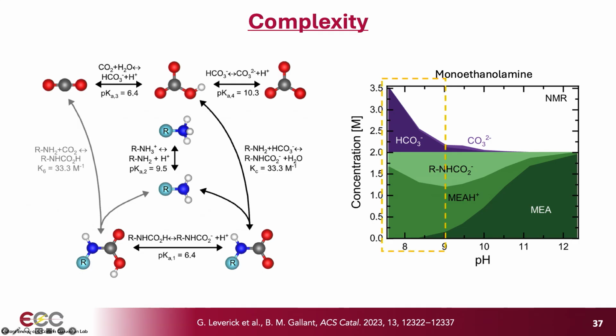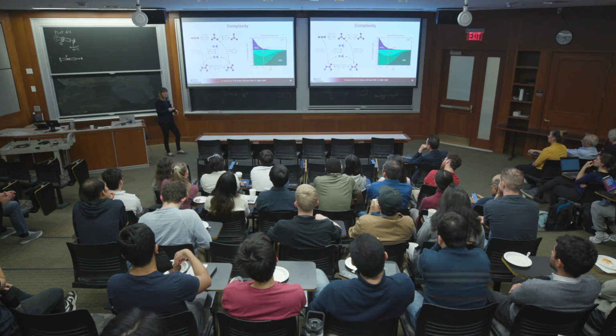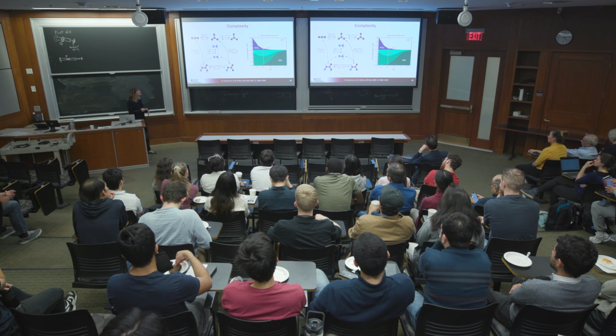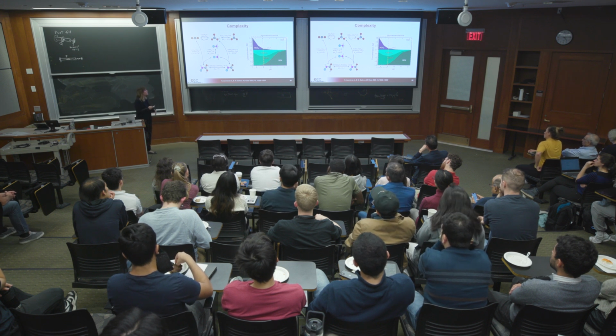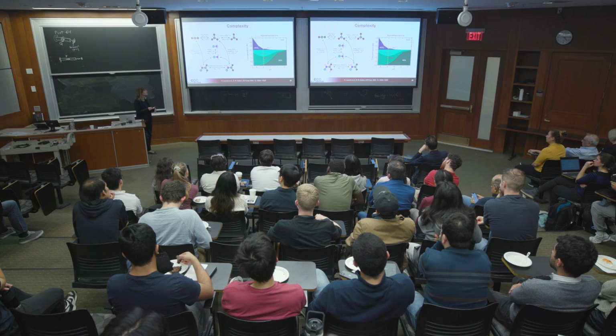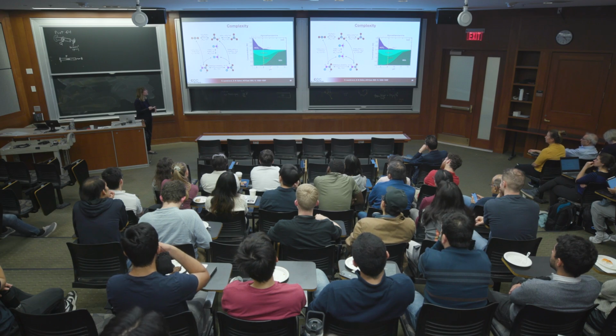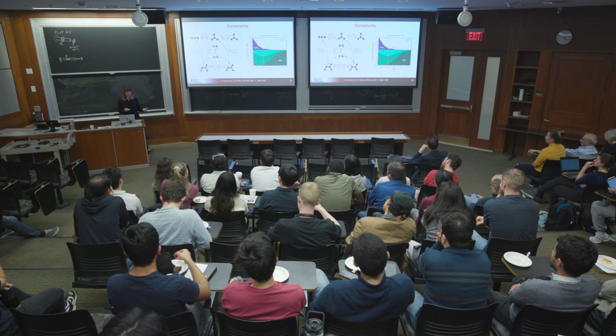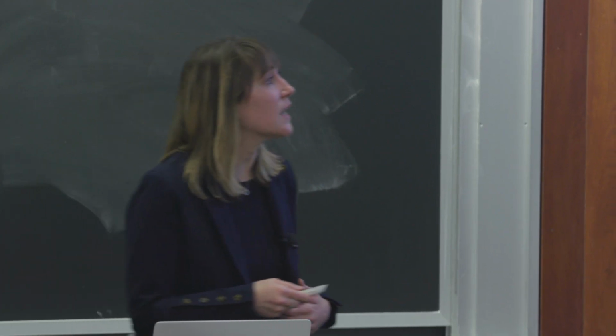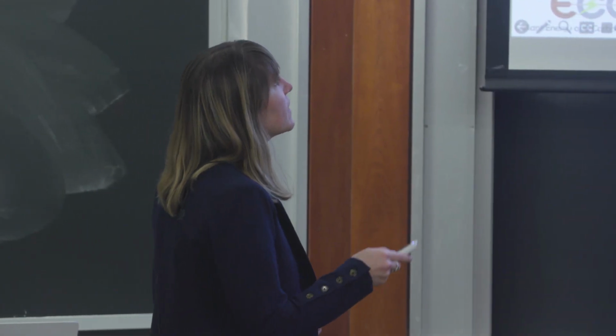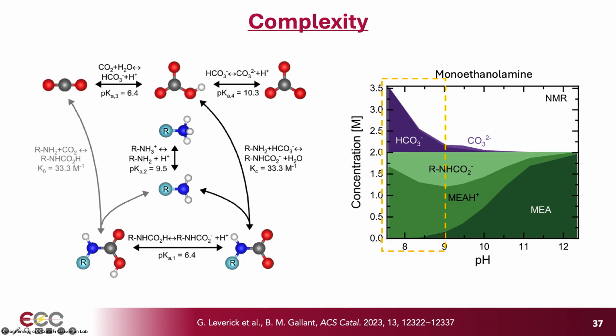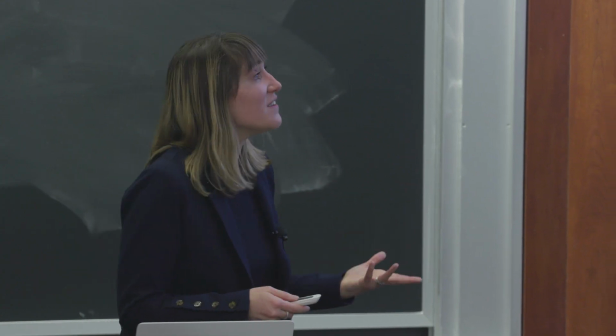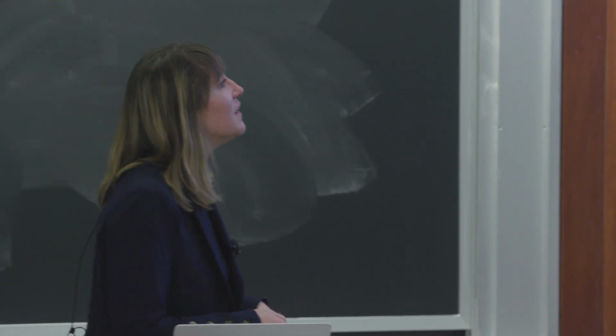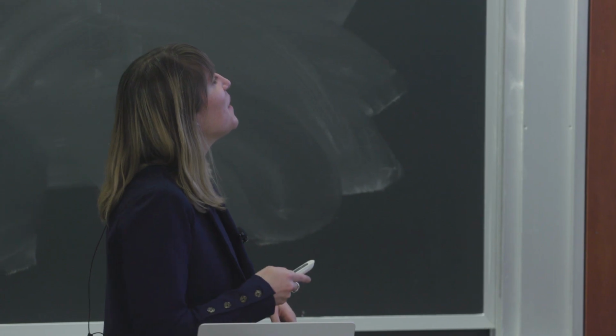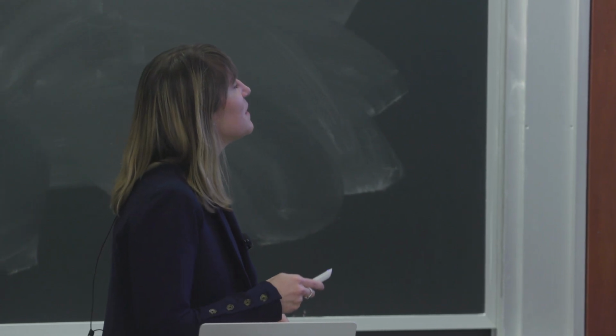One thing I want to emphasize is that the pH for us is actually a design variable in these reactions, because when we first assemble the cell, there's no CO2 in there. We're typically at high pH. And as we bubble the CO2 into the cell, the pH drops. Where we wind up and stabilize is going to depend on the partial pressure of the CO2 in the stream that we're trying to capture CO2 from. But generally speaking, we're working somewhere in this range. And all I really want you to take away from this is that we have quite a mix of reactants here. So figuring out what is the active species for a given reaction is non-trivial. Nevertheless, we have tried. So this really frames the complexity.